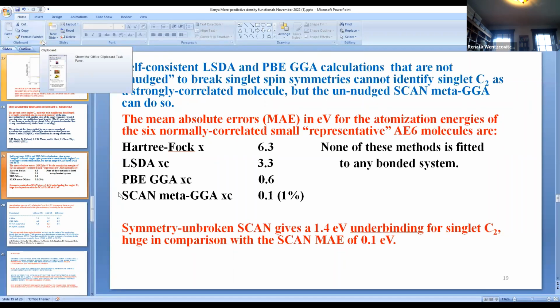If we do SCAN without letting the symmetry break, if we don't nudge it into symmetry breaking, SCAN gives a 1.4 electron volt underbinding for singlet C2, which is huge in comparison to the typical SCAN error of 0.1 electron volt for a small molecule.